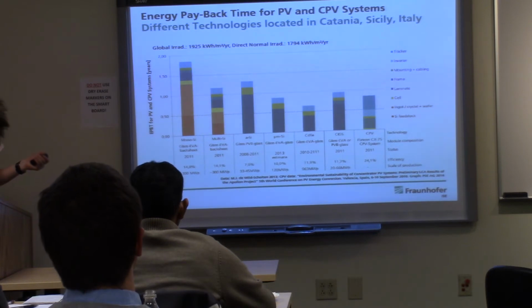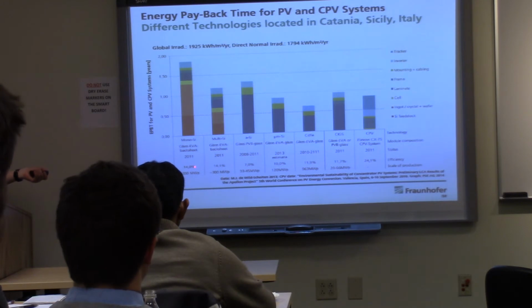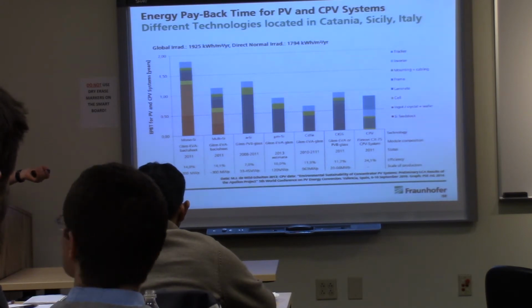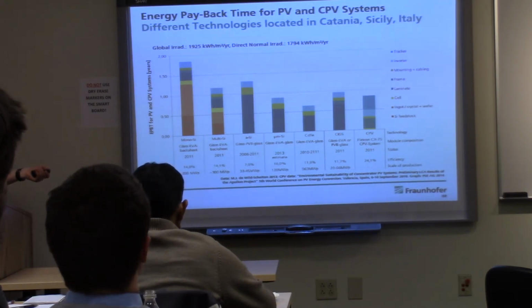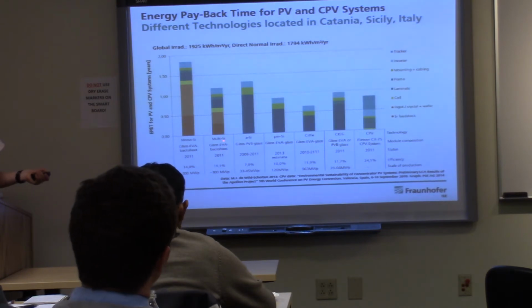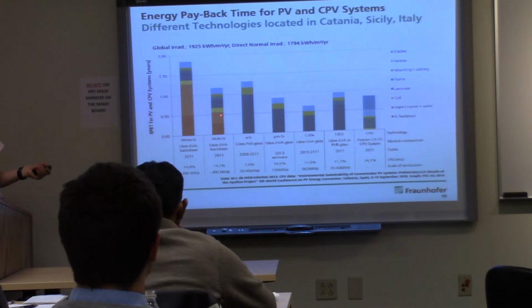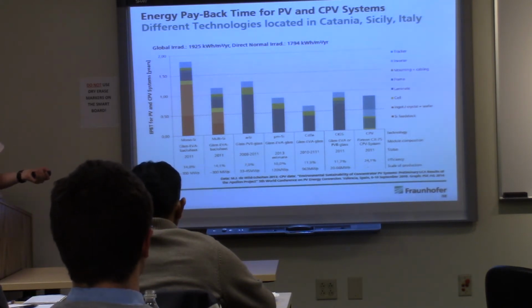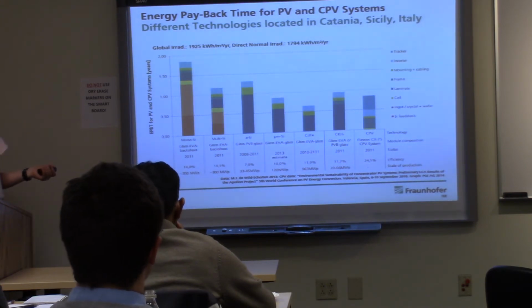And you're at almost 2 years to get the energy paid back out of this thing, even though the efficiency on these is, here it's probably too low. At 14.8%, they should be higher. But that's a long time. At a similar efficiency for multicrystalline silicon, because you don't have quite as much energy going into the silicon production, you're at a little over a year. Amorphous silicon, not that the stuff takes too much energy to produce, but the efficiency at 7% is just so low that you can make calculator solar panels forever without actually making enough to pay one back.